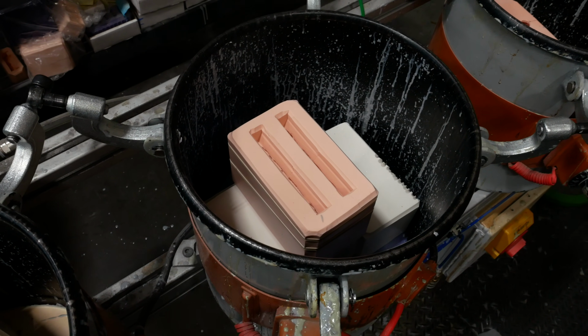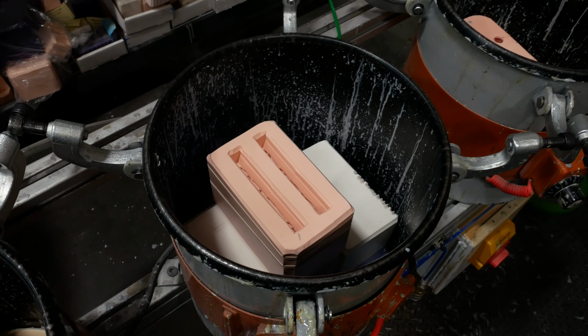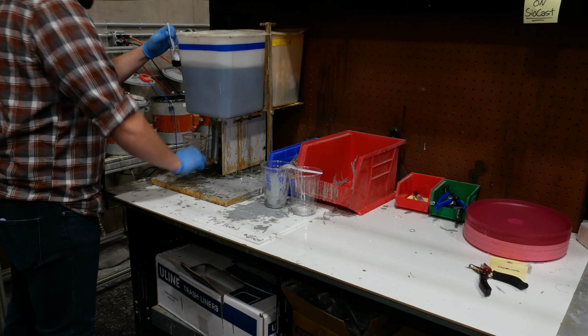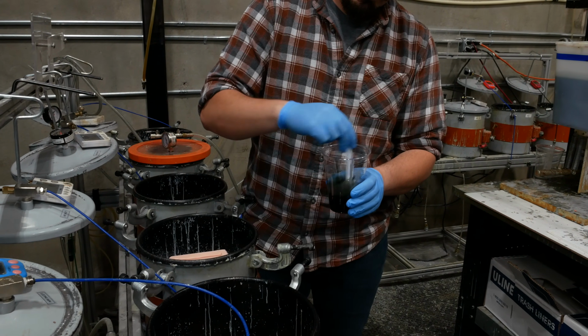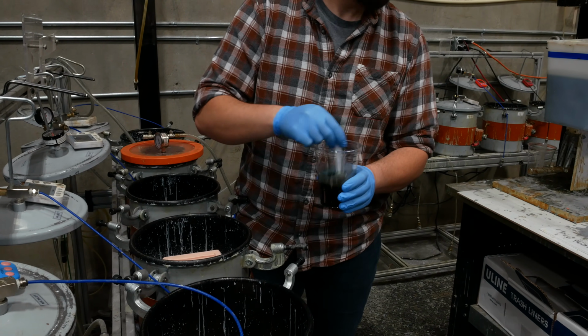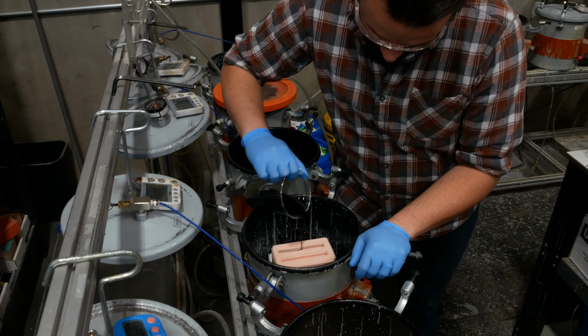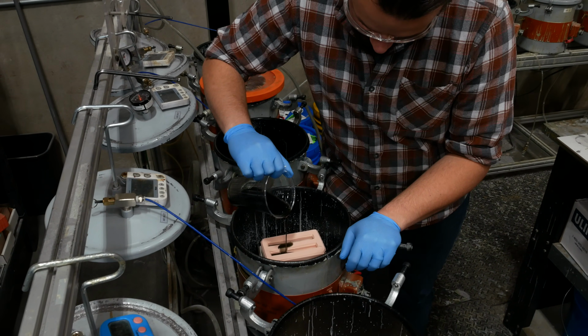For casting, the mold is placed into a pressure pot, and it's not going to move until the resin has solidified. The resin is a two-part mixture. Equal measures of parts A and B are pumped into a cup, mixed, and then poured into the mold. Those big slots funnel right into the sprue and down into the cavities for each of the bits.